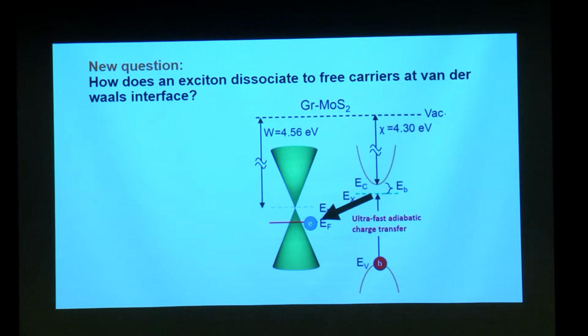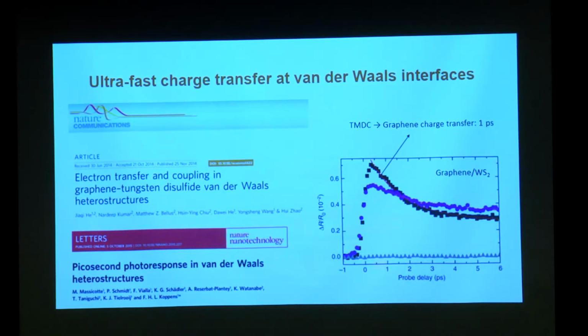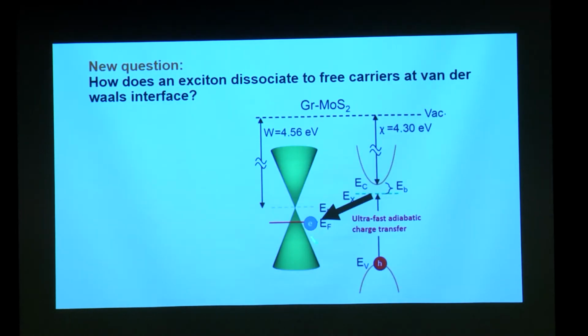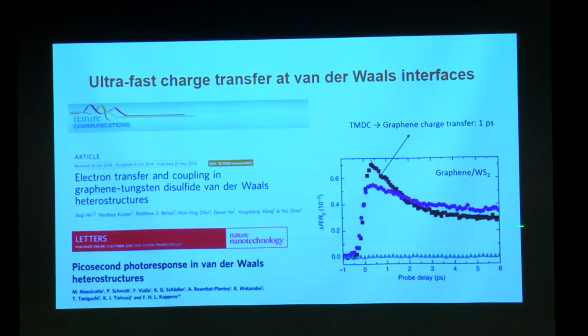So the question is, is it very fast? The answer is yes. This particular transfer, because it's a coherent transfer, happens within a picosecond. This is the pump-probe experiment that had been done by this particular group, and they showed that the electron transfer from the molybdenum disulfide, or here it is the tungsten disulfide, goes into graphene within about a picosecond. The exciton splits within a picosecond, and the electron is in graphene.